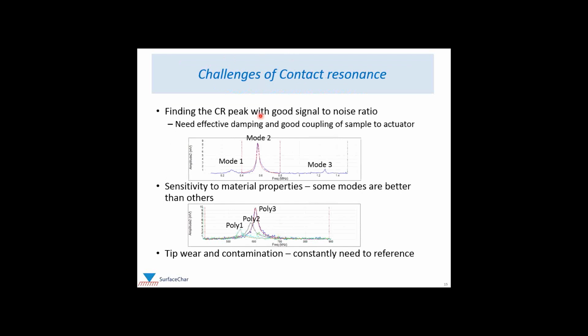So some practical challenges with contact resonance. Probably the number one practical challenge is finding your peak with a good signal-to-noise ratio. In order to achieve that, what you need is effective damping and good coupling of your sample to your actuator.